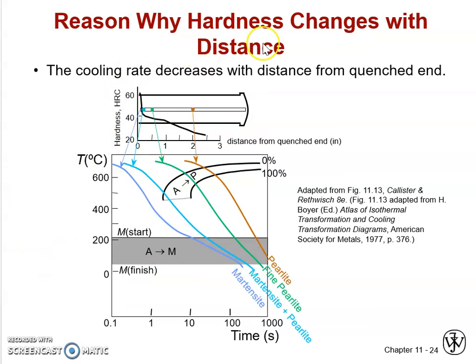Okay, now the reason why hardness changes with distance. Like I said before, if you go back to the TTT diagram, here is the steel. Okay, this is the water jet. The water jet at this point means that the distance is very near to the water jet. So at 0 inch, which means the water jet is very near to the steel, you can see in this graph that the steel forms 100% martensite. As the distance gets farther away from the water jet, it will touch pearlite. Okay, so the steel has martensite and pearlite, so here the hardness becomes lower.